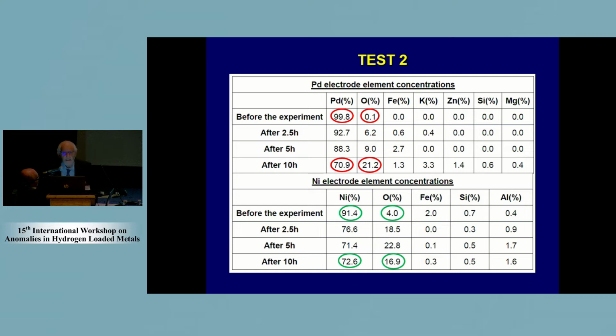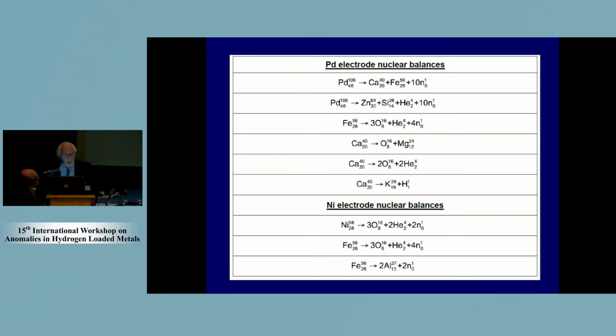Then we had the other 3 tests. They were shorter because we decided that in the second part there were not such important transformations. And I emphasize the extreme values before the test and after 10 hours. But we have also after 2.5 and after 5 hours. So I have not the time to go to the details, but it's very interesting to see that statistically there is an impressive repeatability of the results from the chemical point of view. So we have the assumed fission reactions with neutron and alpha particle